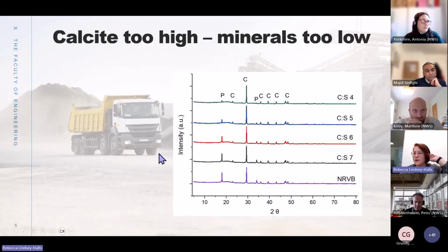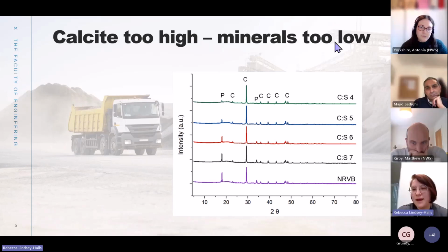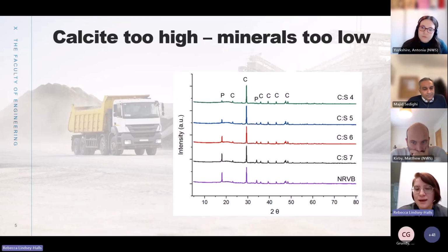Cool. So these were initially cured at room temperature, 80 degrees and 200 degrees, and silicon dioxide was added so that we had the ratio of NRVB, which is 7.27, then more silica was added to reduce it to 7, then 6, then 5, and then 4. This is because there's already quite a lot of research up to a calcium to silica ratio of 3. So these are the XRD patterns that I got when the NRVB cement was cured at 200 degrees.